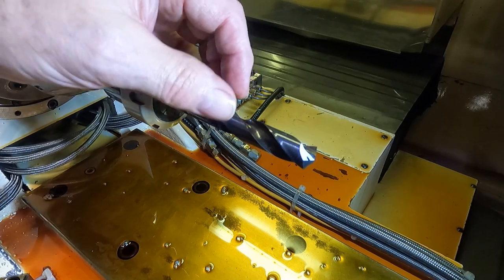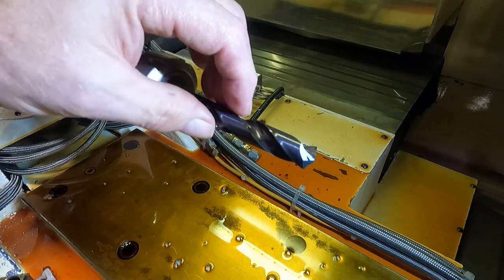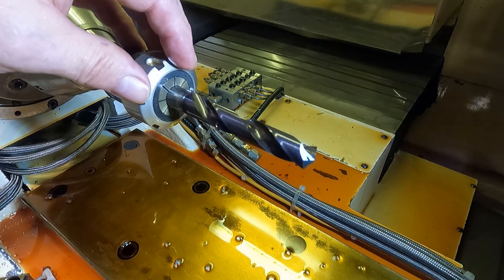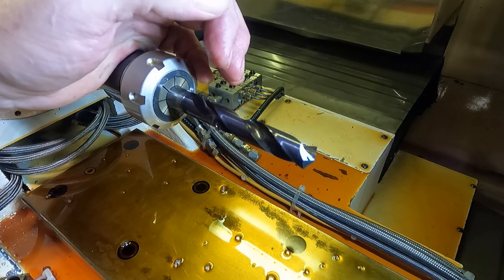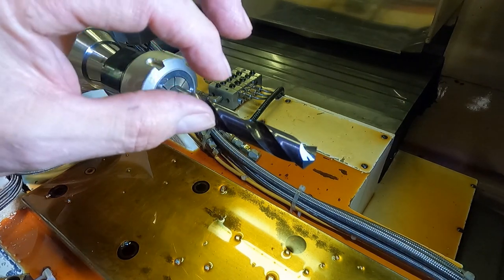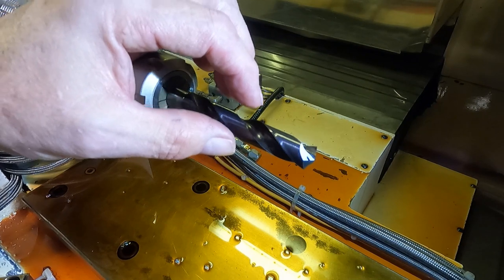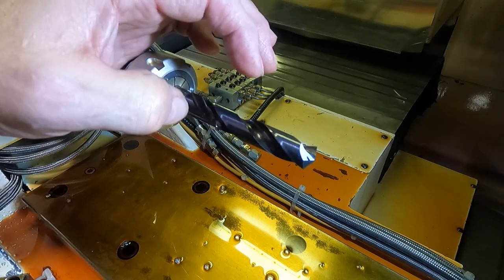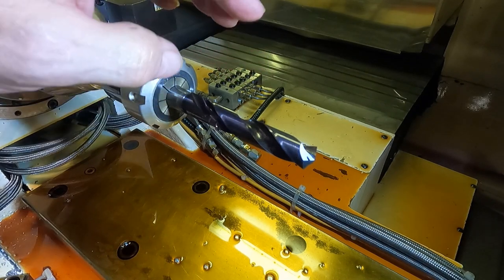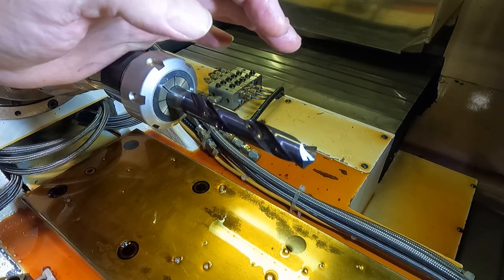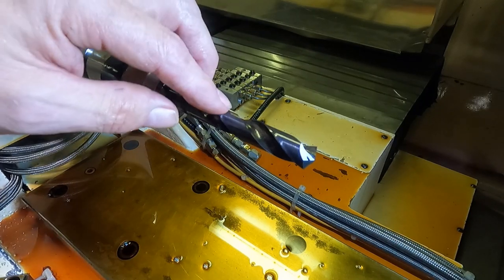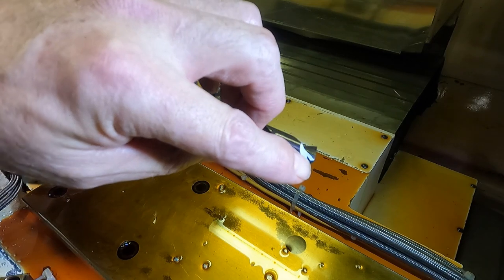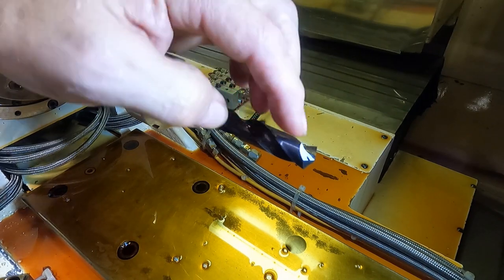I'm not sure. They use different kinds of materials to actually bind the carbide grains together. So it's this fine powdered material is cast in a mold sintered and everything kind of melts together in the sintering process. And it also shrinks a certain amount. So they have to control that when they make carbide inserts, they have to be careful to know those values exactly. So the carbide insert for a lathe turning insert comes out to the right size or milling inserts too, because a lot of the features on those inserts aren't actually ground. They're cast in. You can see that we like the chip breakers and stuff on the top of the tool and everything. And even some inserts on the cutting edges aren't even ground. They just as cast. So you have to make sure, you know, the shrinkage precisely, which they do. So they, they sinter it and then they, then it already has the holes in it. And so when I get the blank to grind it, if I do that and I've done it before you probe the coolant holes